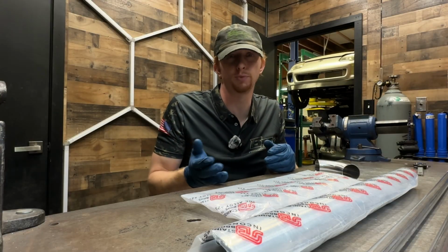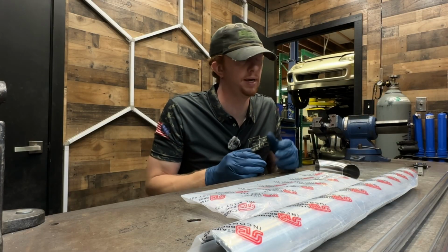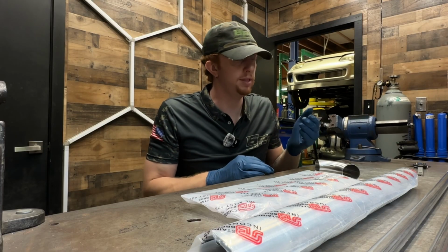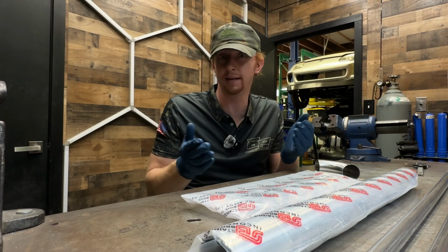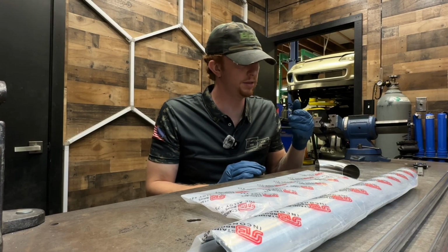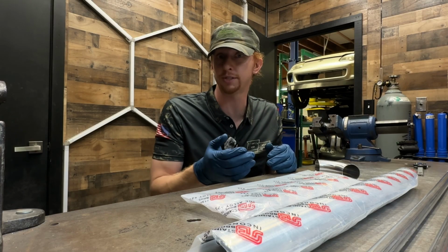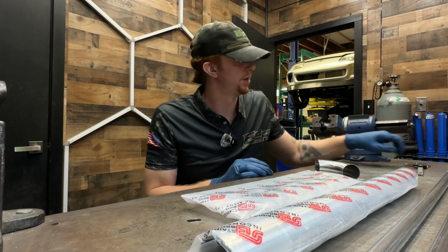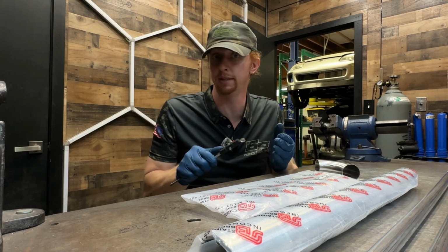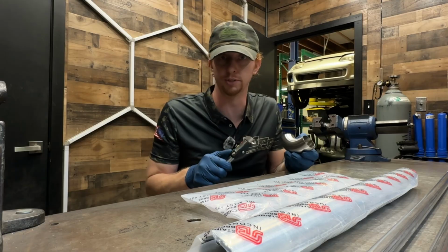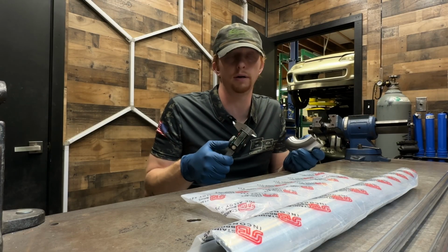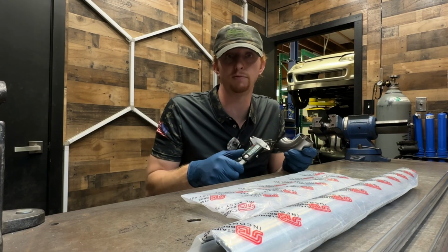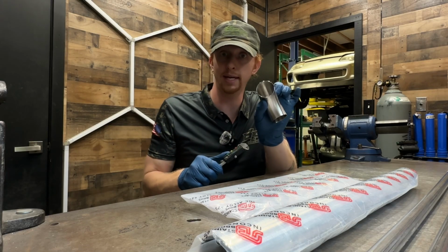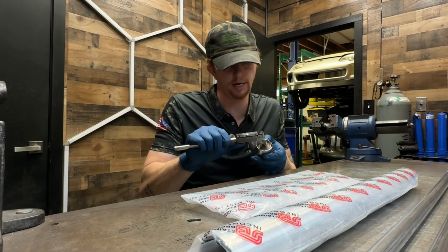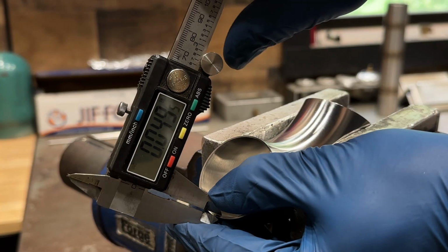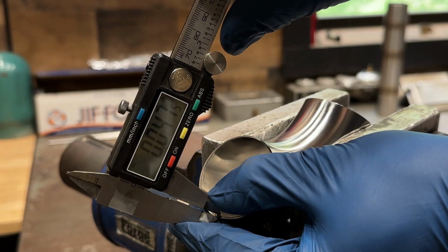So why use Inc. 625 over stainless steel? That's a very good question. Well, the first of a litany of different reasons why is the thinner wall thickness. And what this equates to are lighter parts. So compared to a normal stainless steel elbow that Stainless Bros would sell, that is 0.065 wall, 16 gauge, these Inc. 625 elbows, if I measure it out, they end up being 43 thousandths wall right here.